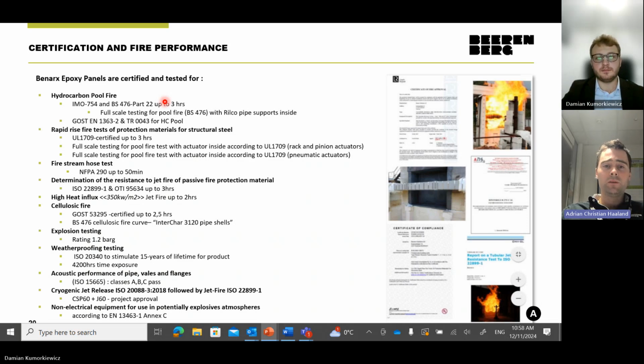The most common fire types that we encounter are hydrocarbon fire curves like BS 476 or UL 1709, and jet fire according to ISO 22899. We also see a lot of high heat flux jet fire, which now is finally coming out with a recognized ISO standard, which is very good for the industry. Explosion testing. In the later years, we've done more of cryogenic testing, which I will come back to. And also some curiosities like fire water stream hose testing.